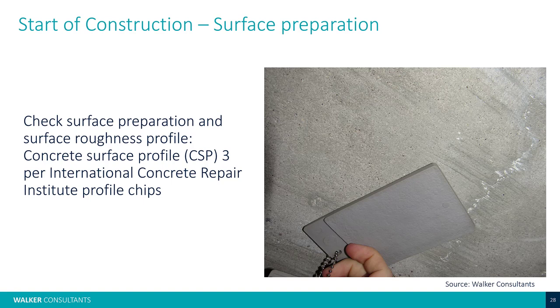Sure. So for the recording purposes here, we have a contractor in the audience, and he did verify that typically 3 is your most aggressive surface profile, and they do vary by manufacturer. So he's seen CSP 2 to 4 surface roughness as required by the manufacturer. So again, you really want to pay attention to that. And he was also stating that a lot of times you do not want a more aggressive surface profile just due to the potential for air voids and things like that to occur behind the product. So thanks for that, Joe.